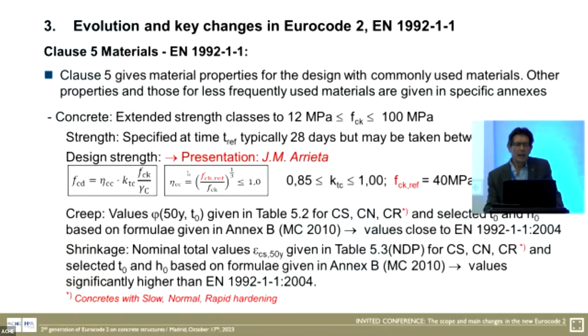It is, as you can see, up to a recommended value of 40 MPa strength, this coefficient is always 1. And if you go beyond 40 MPa strength, then this coefficient gradually comes down and reaches about 0.85 at the strength of 100 MPa. I will tell you later on what the advantage of this is when I come to